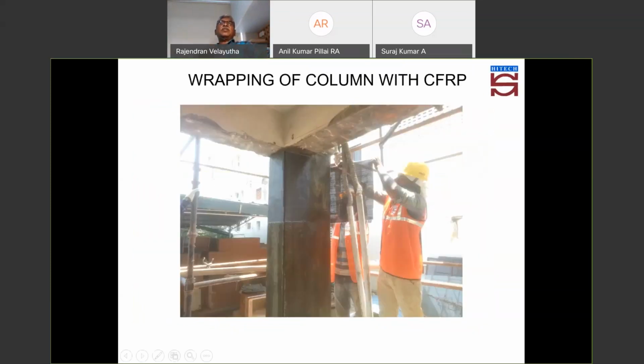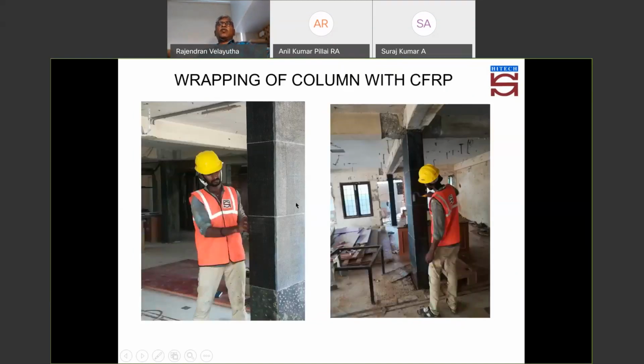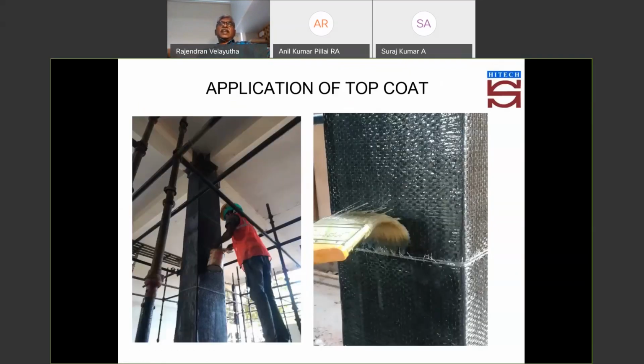And then it is wrapped, in this case with a 230 GSM fiber wrap, where you get confinement and increase the strength of the concrete. Once it is wrapped, this is how it looks. After the wrapping is completed, we apply one more layer. Here, they are using a ceramic roller to release any entrapped air, so that the bond between the concrete and the repair system is perfect.